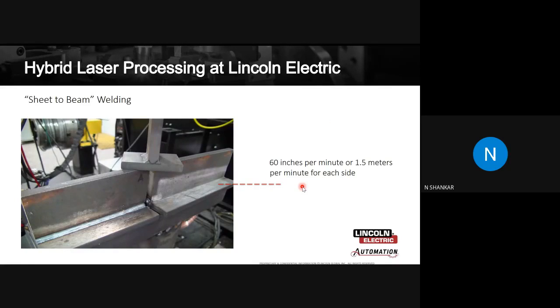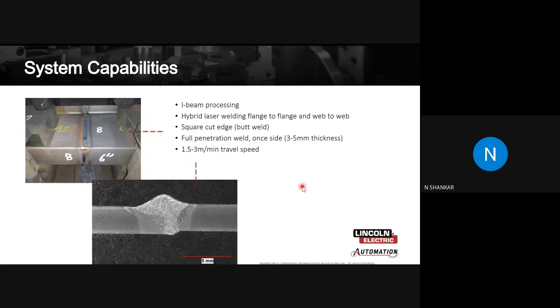It's been used for sheet to beam welding also. Lincoln has used it for beam welding, what you call as the PEBs, or for the heavy beams with a very high speed of 1.5 meters per minute for each side actually. So a very high speed productive solution is hybrid laser welding. It can weld I-beams as I was telling you.